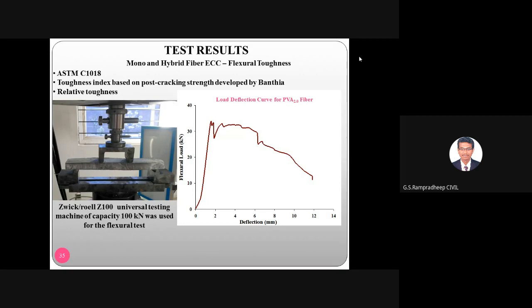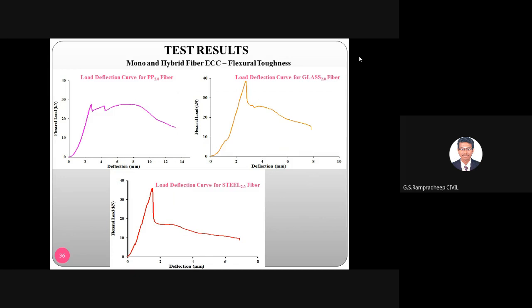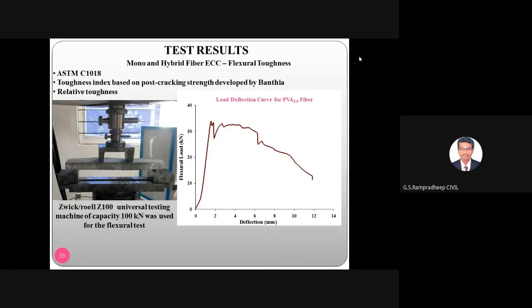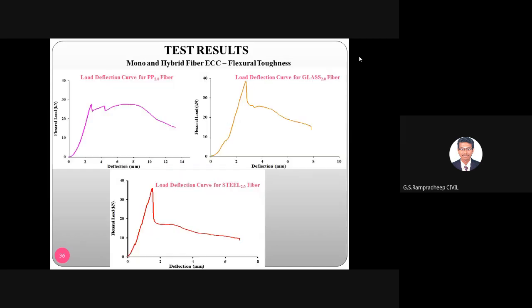A slab material, thin slab material, and for 2-point loading, as per the Zwick universal testing machine of 100 kilonewton, you can see the maximum load carrying capacity of 34 or 35 kilonewton, the peak value, and the maximum deflection is coming around 11.9 or 12 mm. So this is for PVA combination of 2%, and the remaining graphs show, for example, if you take the glass fiber, the ultimate load carrying capacity is around 40 kilonewton. Where PVA fiber, a low modulus fiber, is used, it is around 33, and around 7 to 8 kilonewton is getting different.